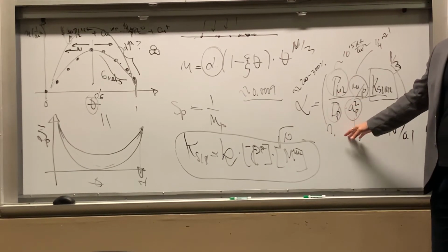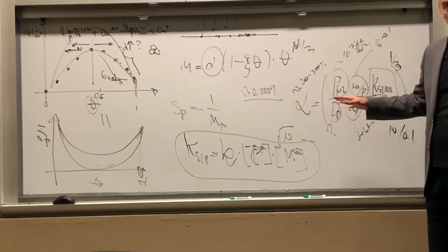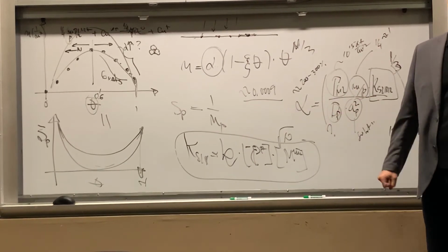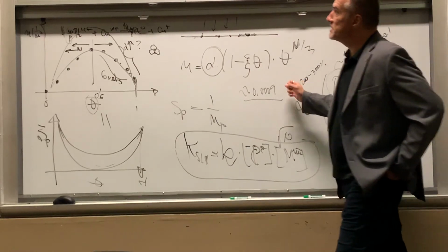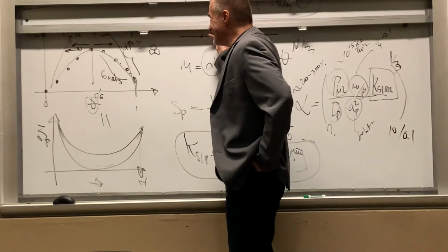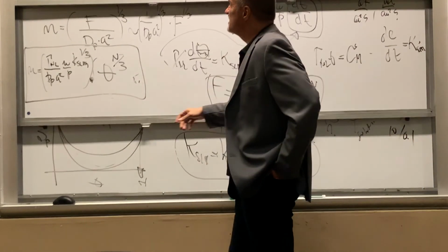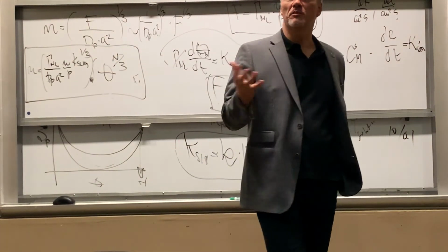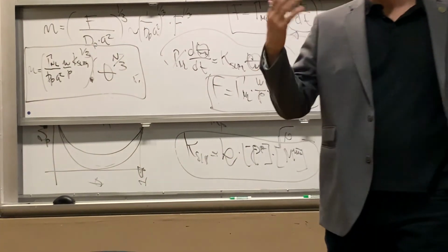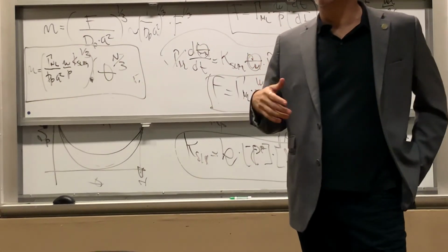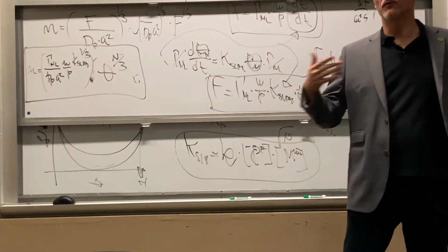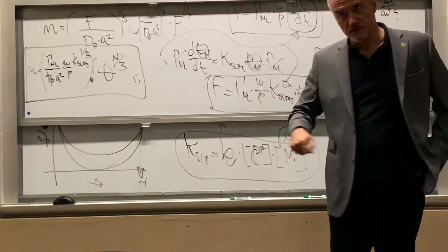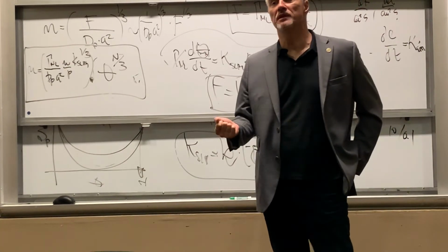There's no technique to measure this. But during this reaction, it turns out platinum is super fast on the surface. And if something is super fast on the surface, it turns out it promotes 2D growth. If you remember nucleation and all this stuff, one of the ways to force 2D growth is to increase diffusivity on the surface, which means you go up with the temperature.